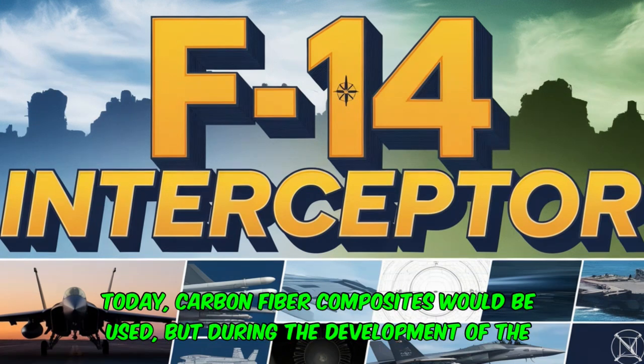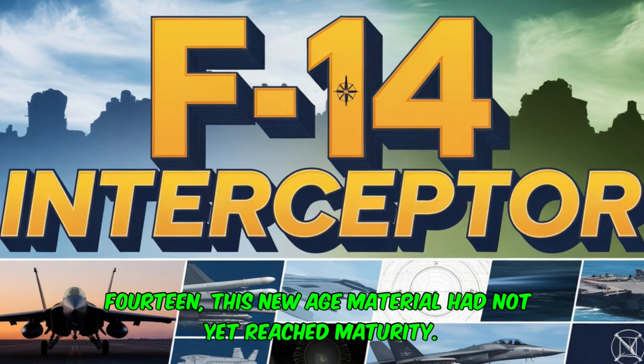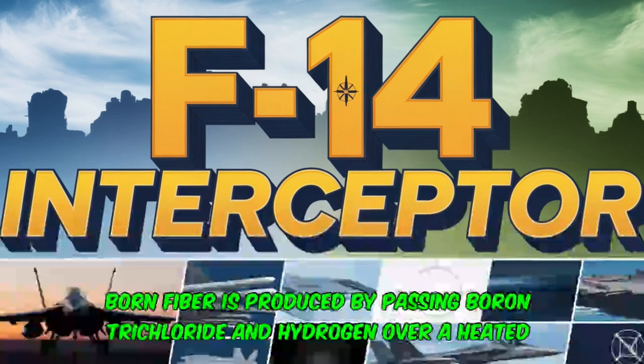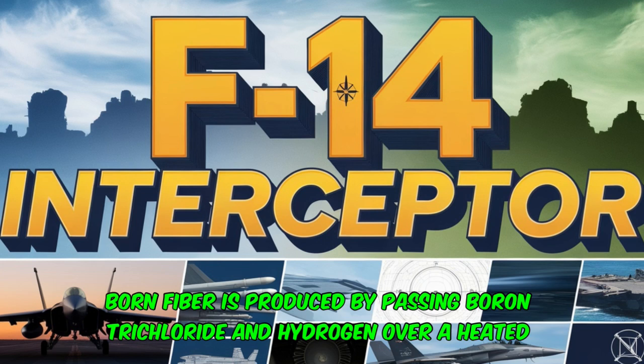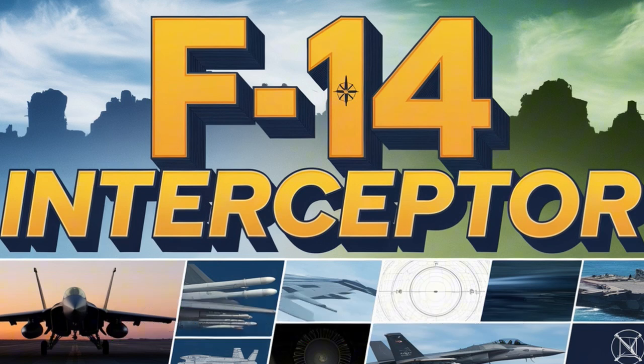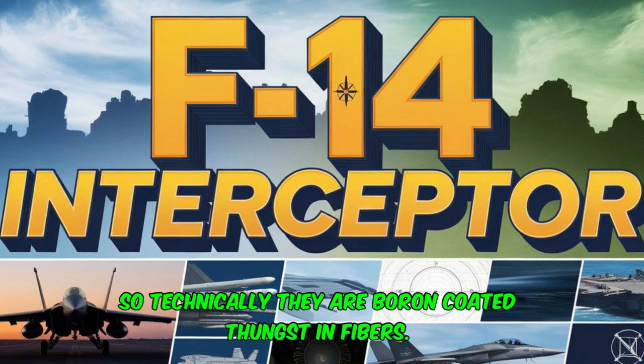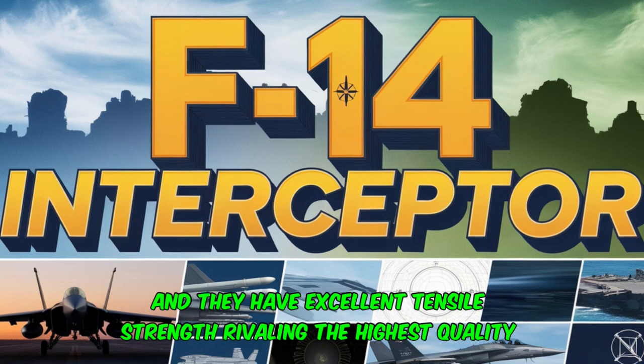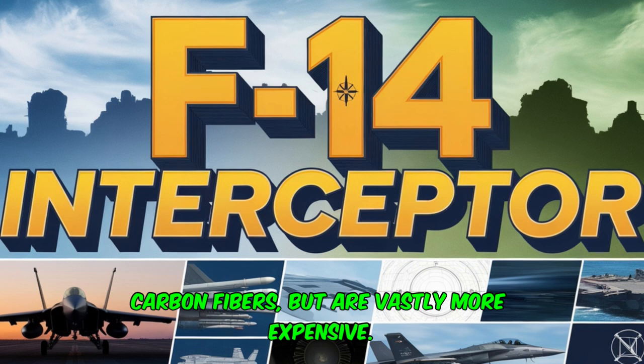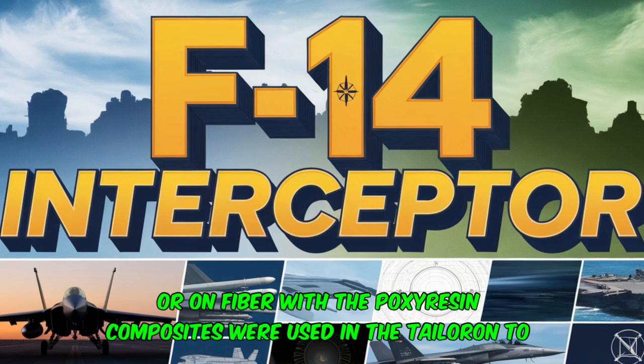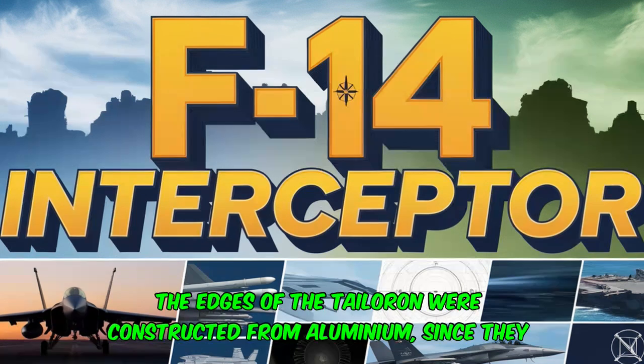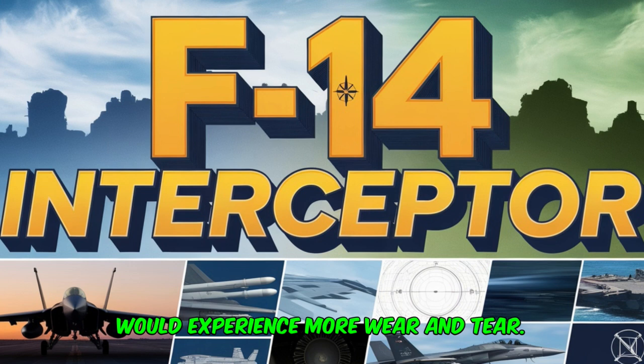Today, carbon fiber composites would be used, but during the development of the F-14, this new age material had not yet reached maturity. Boron fiber is produced by passing boron trichloride and hydrogen over a heated tungsten wire. So technically, they are boron-coated tungsten fibers, and they have excellent tensile strength, rivaling the highest quality carbon fibers, but are vastly more expensive. Boron fiber with epoxy resin composites were used in the taileron to reduce weight. The edges of the taileron were constructed from aluminium since they would experience more wear and tear.